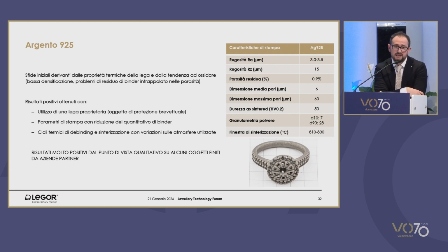Silver has been the first precious material we have worked on. So we started on the metal, because we're starting with sterling silver at the beginning, but the eutectic phase, which is marked in the binary alloy, represented a problem for densification. So this is why we changed the formulation to minimize the problem.